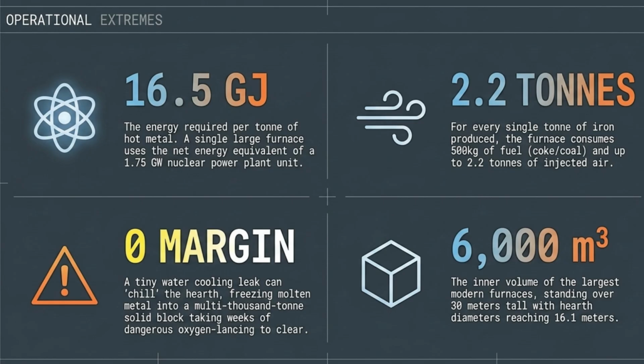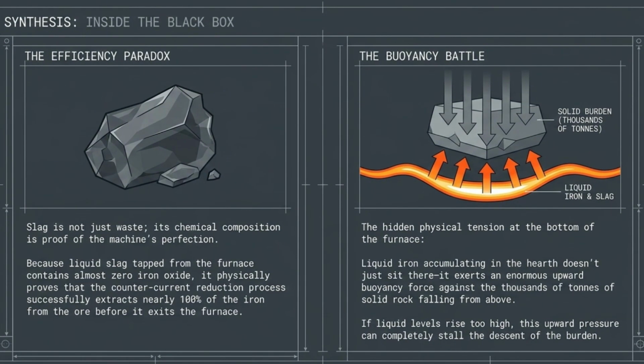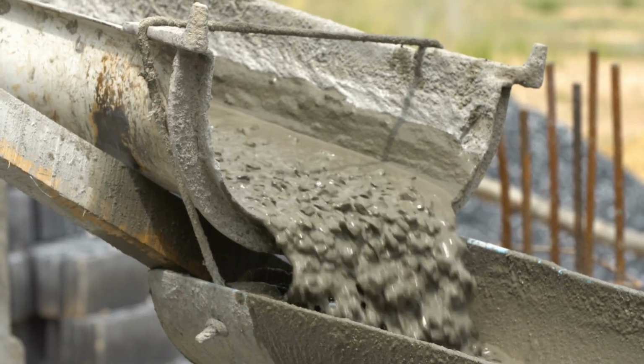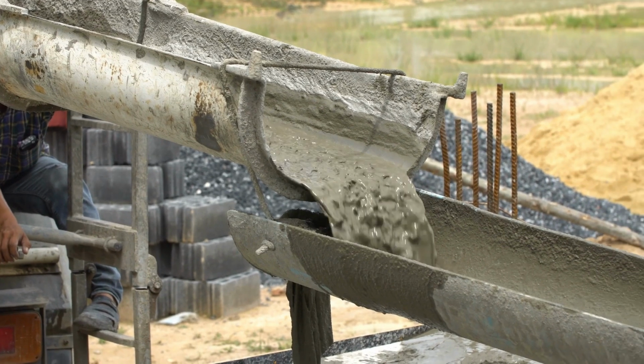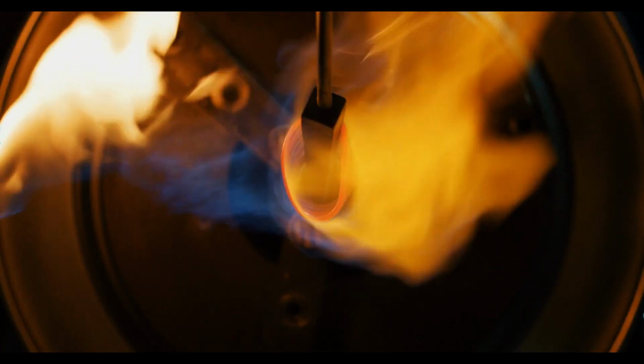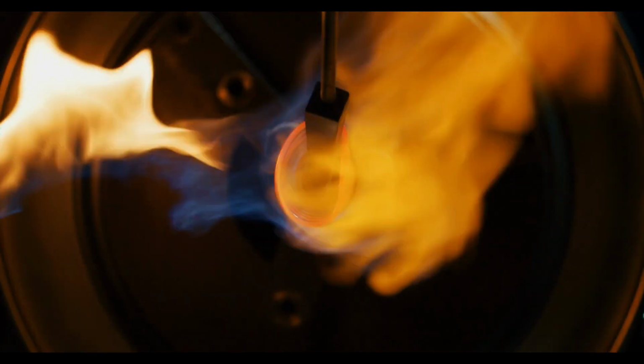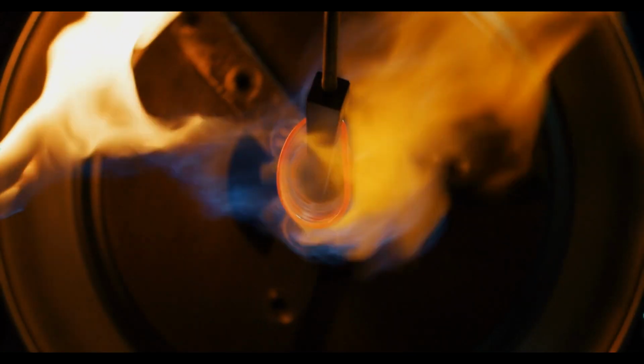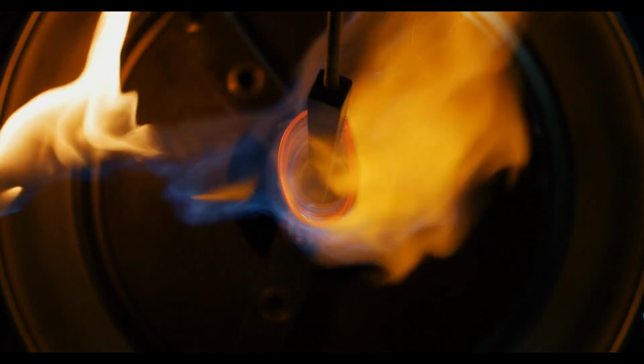The slag that pours out alongside the iron contains almost zero iron oxide, proof that the furnace has captured essentially every useful atom from the ore. And that slag is not waste. Depending on how it is cooled, it becomes road aggregate, a key ingredient in cement, mineral wool insulation, or glass-making raw material. The byproduct of iron production is quietly inside the walls of your house.